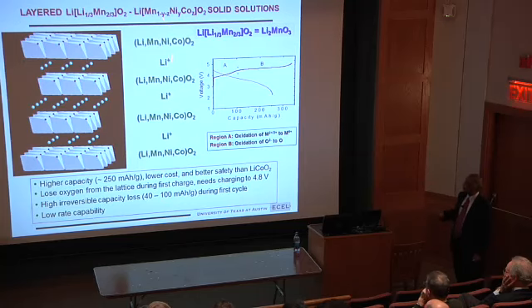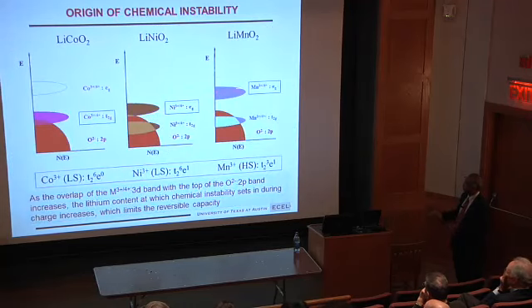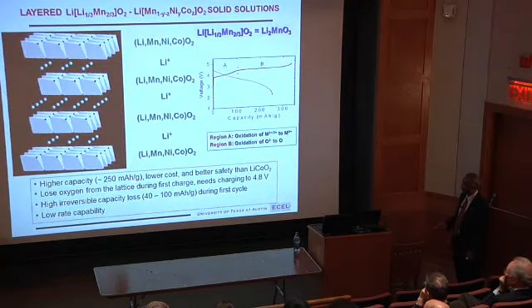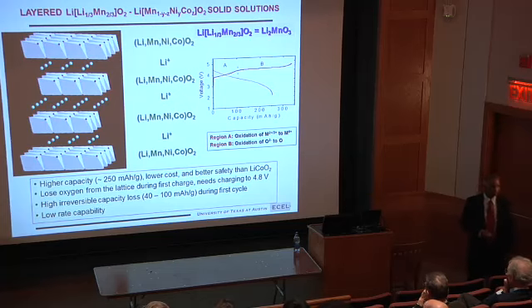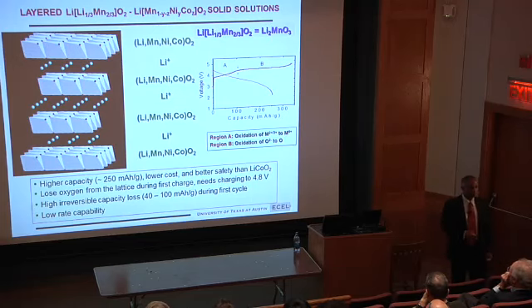And also, it has a lot of manganese and a little bit of nickel, small amount of cobalt, so cost is low. It also has better safety, like I pointed out earlier. You see, these have better safety than cobalt oxide. But it has a few problems. You have to charge it to 4.7 or 4.8 volt. That's a problem. Electrolyte can become a little bit unstable. And it also loses oxygen from the lattice in the first cycle.